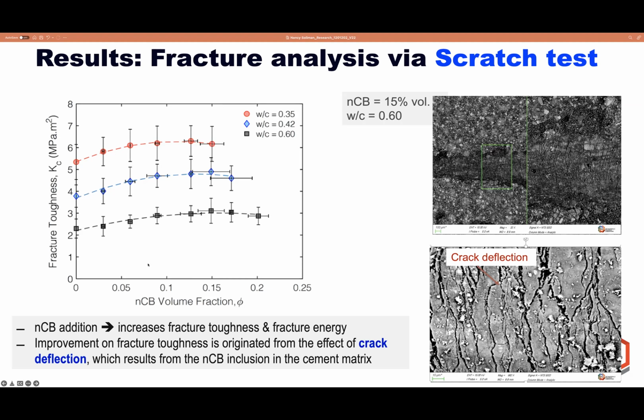This slide shows three different water cement ratios, from water cement ratio 0.35 to water cement ratio 0.6. What we observed here is that the addition of nanocarbon black enhances the fracture toughness of the material, whatever the water cement ratio. And this enhancement in the fracture toughness originates from crack deflection. So crack deflection means that the crack doesn't go through the nanocarbon black inclusion, it goes around it, requiring more energy to open the crack. So the nanocarbon black is considered an obstacle in front of the crack.